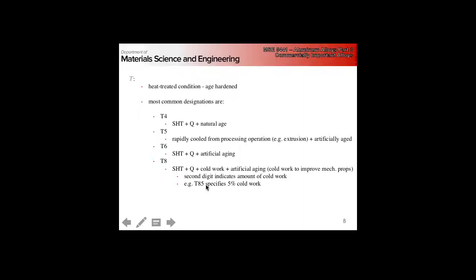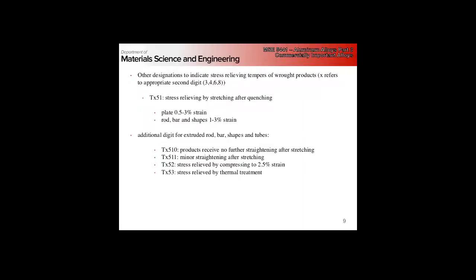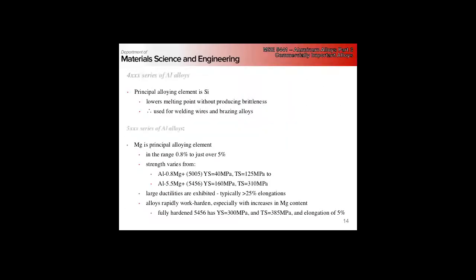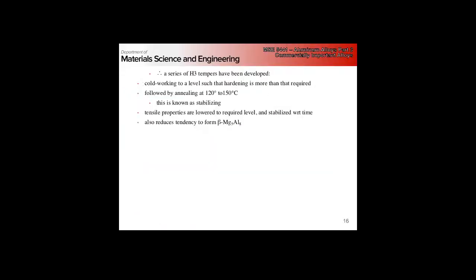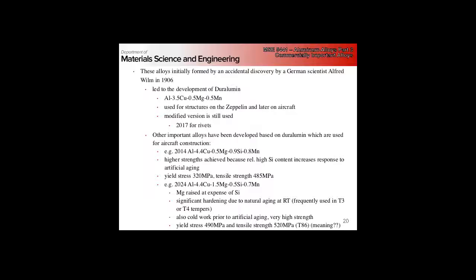If you have two additions, two after—so T851, which comes up, means it's the T8 temper plus an additional stress relieving after it. They do that just because once you precipitate your second phase, you have some extent hardening from plastic deformation. You mean the rationale for the T8? Yeah, well, it's just to leverage both hardening mechanisms.